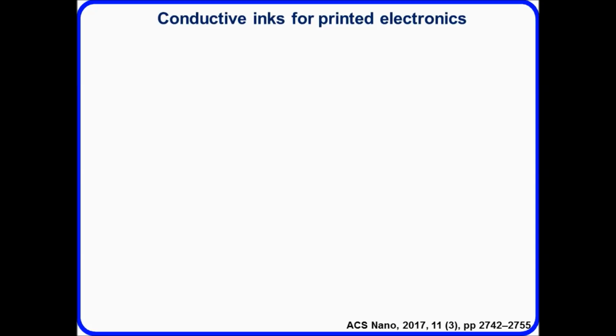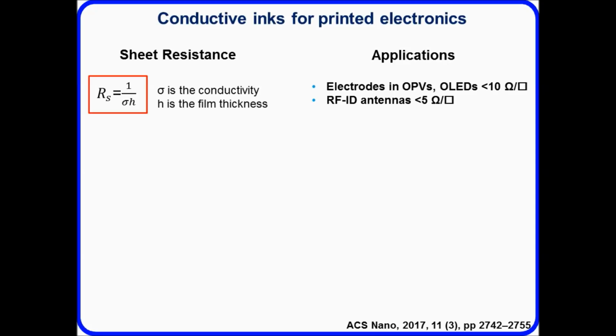So to harness some of these important properties and make use of graphene's potential, we need some way of manipulating and depositing these graphene structures. One way we can do this is producing conductive inks and then printing them using different techniques to produce conductive circuits and electrodes. The performance of these devices is typically compared using their sheet resistance. For applications, for example, electrodes in organic photovoltaics or OLEDs, we need materials with sheet resistance less than 10 ohms per square. For radio frequency tags, we need something on the order of less than 5 ohms per square.